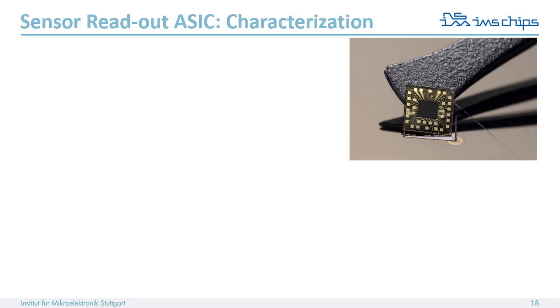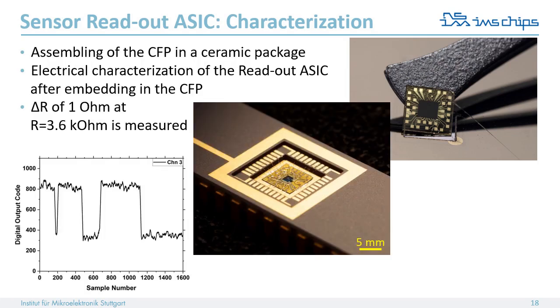in the ChipFilm Patch. After the release from the silicon carrier, the ChipFilm Patch was also assembled in a ceramic package, depicted here in the middle of the slide. The graph on the left side shows the signal response from one measured channel at 3.6 kilo ohm. The change in the amplitude corresponds to 206 microvolt, which is consistent with the initial test of the ASIC before the embedding. The embedded readout ASIC shows the same functionality behavior as before the embedding in the polyimide.